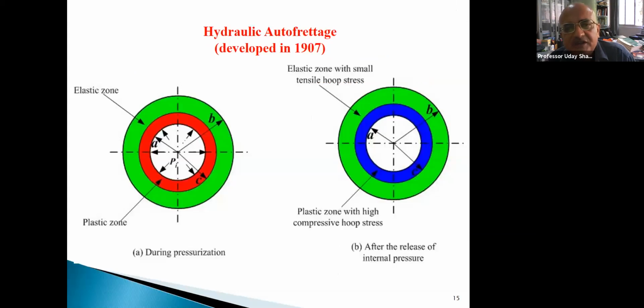Another process that I would like to mention, which was of course developed in 1907, is hydraulic autofrettage. But this basically imparts residual stresses. There is a difference between severe plastic deformation and autofrettage. In autofrettage, basically I am producing residual stresses on the surface. I can increase the strength of the material by strain hardening, and by means of that, microstructural changes. But I can also increase it by putting in residual stresses. If I put compressive residual stresses on the surface, then they can improve the fatigue strength also.